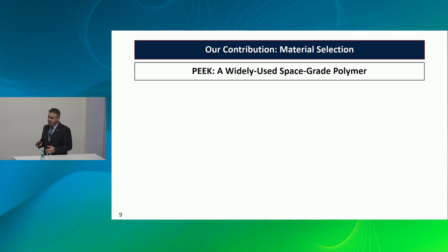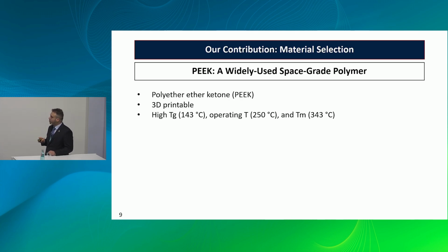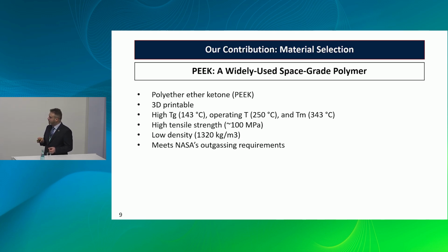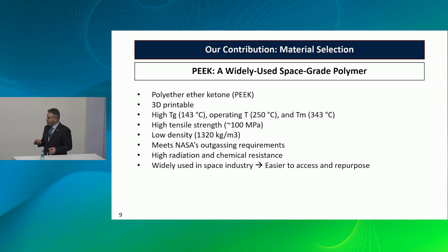So now the second part of the presentation, about our contribution. PEEK is the polymer binder selected for our research because it's a widely used space-grade polymer. It's polyether ether ketone, and it's 3D printable. It can withstand high working temperatures of around 250 degrees. Tensile strength is very high compared to many polymers, around 100 megapascals, with low density, and it meets NASA's outgassing requirements. It offers high radiation and chemical resistance. It's widely used in the space industry, so there's potential for PEEK to be easier to access and repurpose compared to other polymers, hopefully in future.